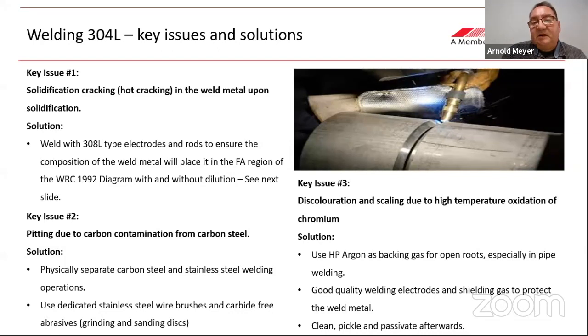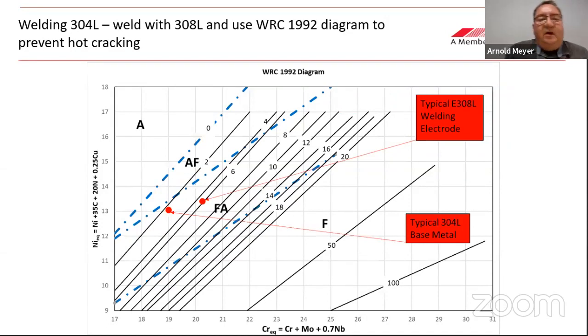The discoloration and scaling: use HP argon as backing gas for open roots, especially in pipes, because after you have welded the pipe, you can't go and clean up there. So you need to purge with an inert gas to stop the oxidation and discoloration. And then good quality welding electrodes and shielding gas to protect the weld metal on the outside. And then clean, pickle, and passivate afterwards. In other words, get rid of that oxide, expose a fresh surface, fresh chromium to the atmosphere, and you will prevent corrosion forming there. If you look at this diagram that I have on here now,